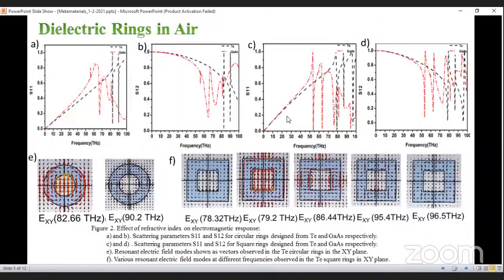So we carried out simulations in air medium, with a comparative study with tellurium and gallium arsenide, to look at the effect of refractive index on resonance characteristics. The electromagnetic wave in the frequency range 1 to 100 terahertz is incident on the rings. Here we observed the resonance frequency of gallium arsenide shifted towards lower frequencies.